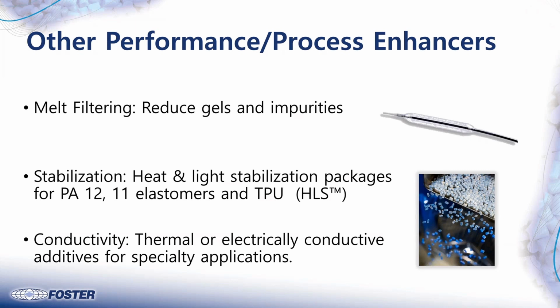We can also adjust the pellet size. We can make very tiny pellets, even micro pellets, if you're going on a very small extruder. Stabilization. Most of the formulations have some kind of heat and light stabilizer, some kind of process aid. Again, we can make all the compounds without it, but these are ingredients that have been tried and true. Many of them we've already had tested for USP Class 6, so they work extremely well, and they give you a little bit more stability when not only you're doing the extrusion of the tube, but also if you have a reflow process where you have to remelt the catheter tube when you're doing the assembly, or if you're doing some heat bonding. If you have a heat stabilizer in there, it could be just the thing that gets you over the hump.